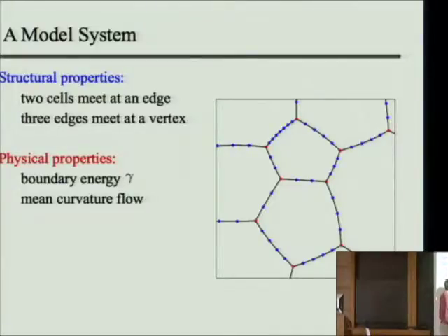Yeah. But it's a function, for example, so in 3 dimensions, this is going to be some crystal. It has some orientation associated with it. So that's several degrees of freedom. You have a number of degrees of freedom for the orientation of the cell on the other side. You have a couple degrees of freedom associated with the boundary plane in 3 dimensions. And then you can have microscopic realignments to cause the crystal lattice to line up on either side. So it ends up being a very complicated thing.